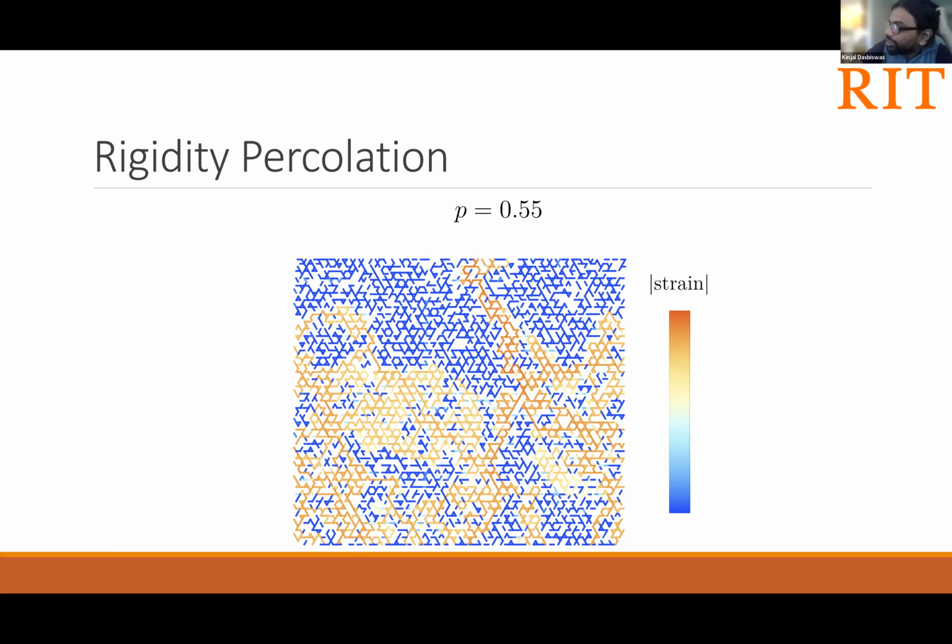So there is a follow-up question related to that. I'll just read it from Andre. He's asking, what is the average coordination number after dilution? Sure. So for the fully coordinated network, one can just multiply that full coordination number by the portion of bonds retained. So here, I suppose 2.2, for instance, would be the mean coordination number for this structure.